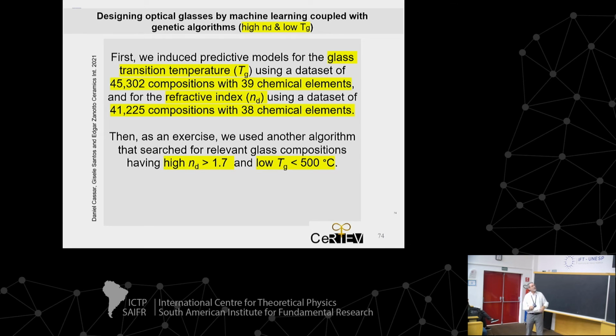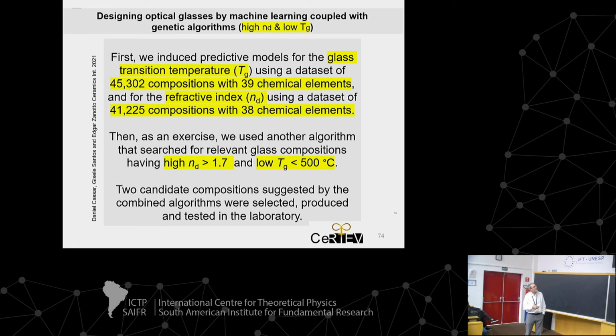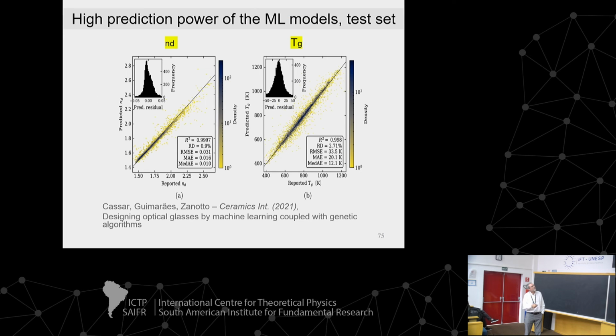And we wanted a glass for a particular application with a refractive index larger than 1.7 and TG smaller than 500. We wanted this glass. Nobody made this glass. It does not exist. You cannot buy this glass. And I, you know, would waste my whole career trying to make this glass empirically, even if I have some knowledge about glasses. So we trained.